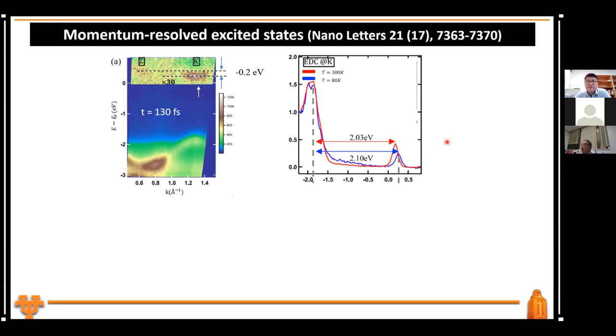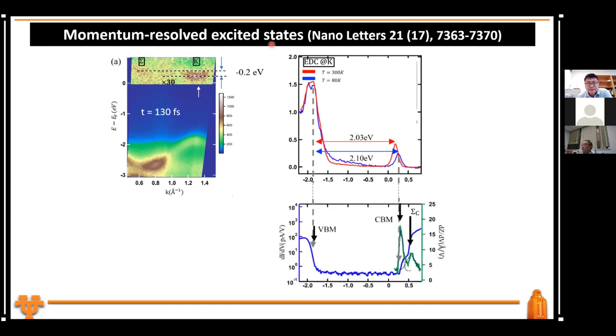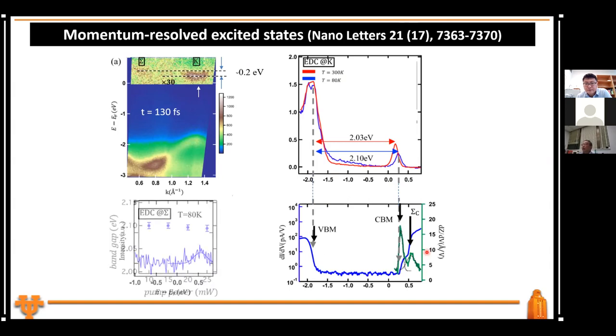Of course, time-resolved ARPES in fact really creates a many-body state, so it is far more complicated than the tunneling spectroscopy. Nevertheless, in this time-resolved spectroscopy, we can see the K point right here. This one is the Q point, although people in photoemission like to call this a sigma point. And the difference is about 0.2 eV. And that is precisely what we see in the tunneling spectroscopy. All right, so that just tells you how you measure the quasi-particle band gap precisely.